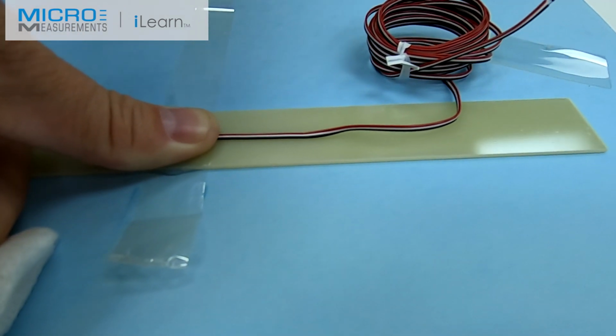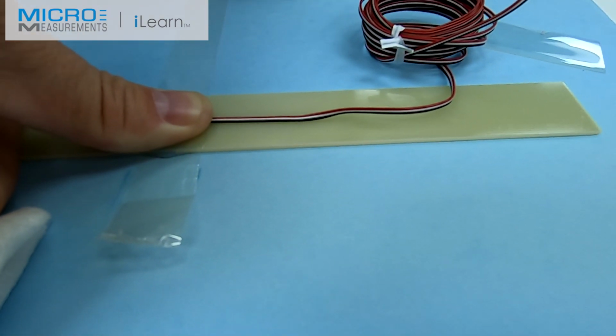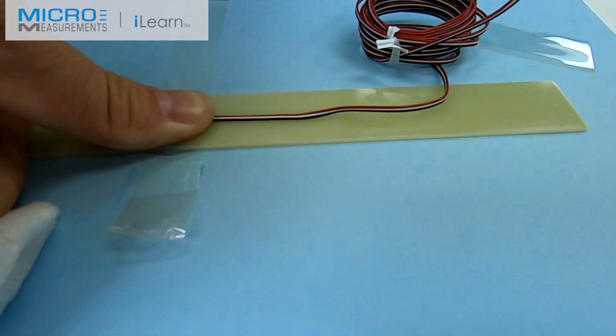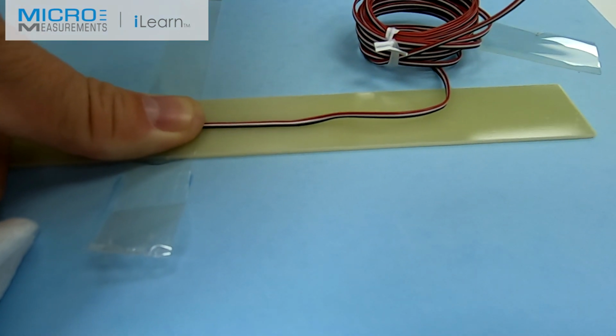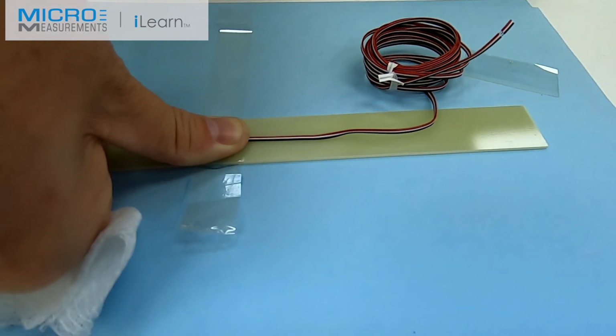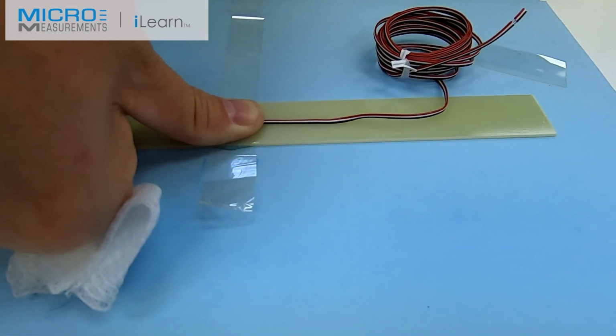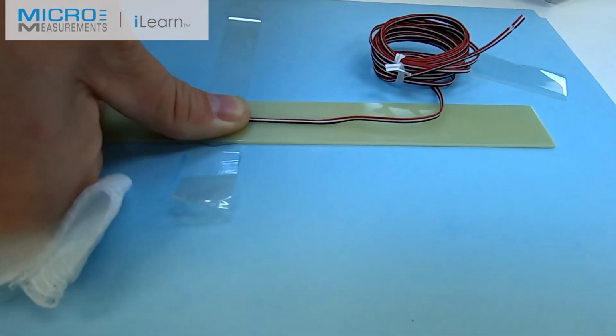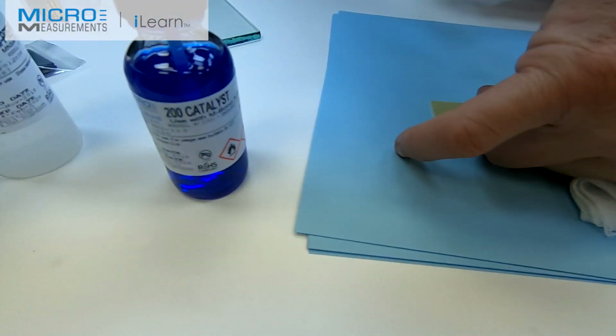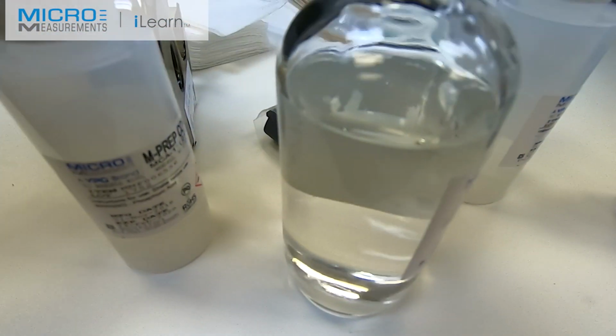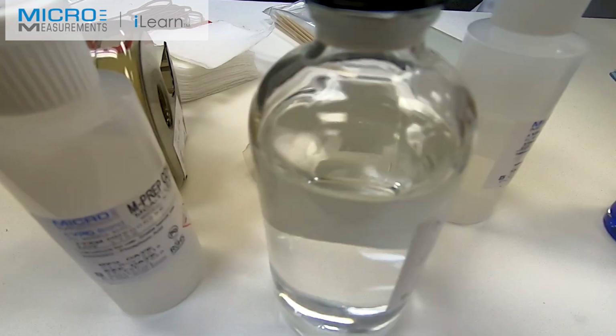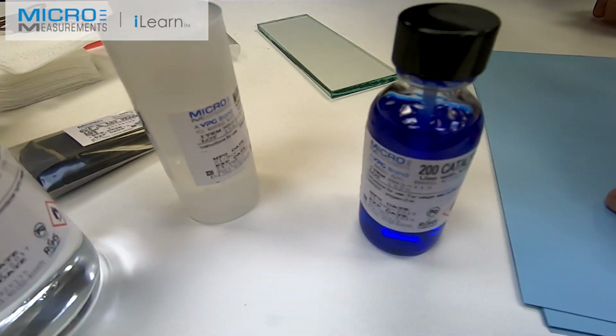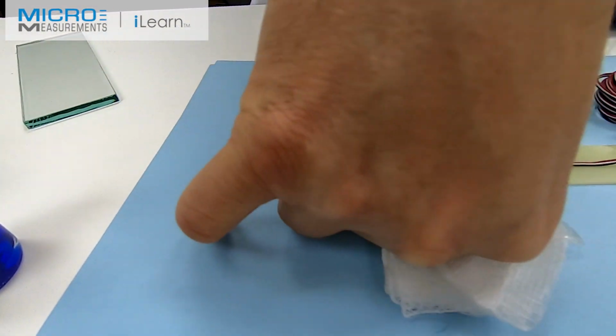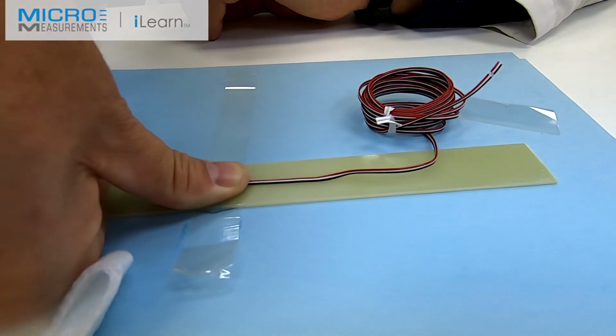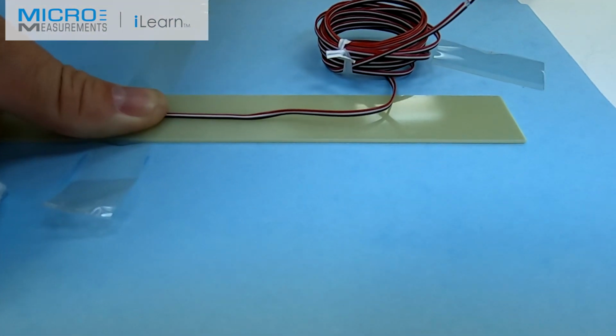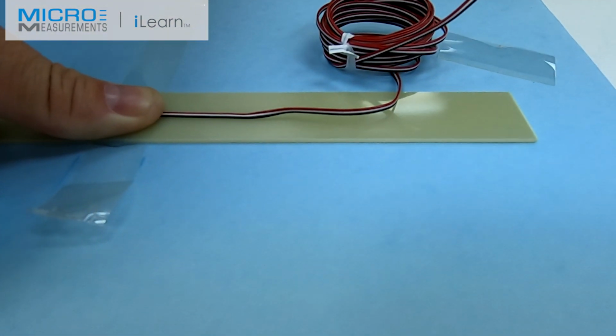A lot of times you'll have gauge problems where you'll have a path to ground that could be a wire stripped back too much and it's touching, or it could be some type of conductive material that's left on it. Most likely source of that is flux. And if you test it and you find that you've got some resistance to ground issues, what you should do is go back and re-clean it. And you do that before you put on an environmental coating, because obviously that makes it much tougher to clean it once you've started applying a coating system.